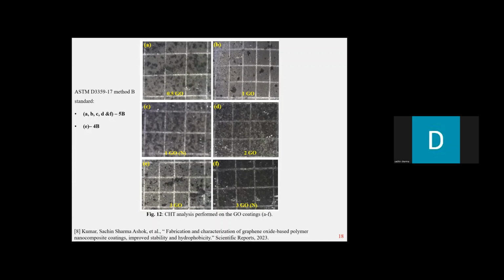However, for the 3 weight percentage GO, for diagram E, we could see that there was some kind of detachment, but it was only less than 5%. So it exhibited a 4B rating. However, all the coatings did not show any kind of cracks, and they were basically intact. And the results here were supported by the EIS as well as the water contact angle.